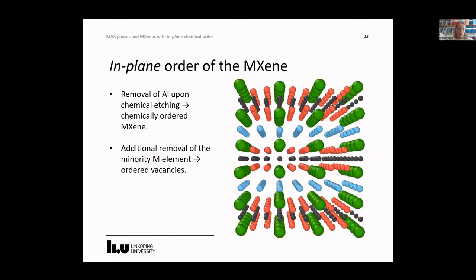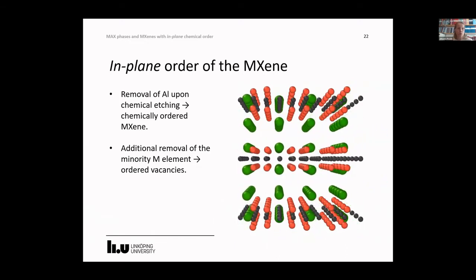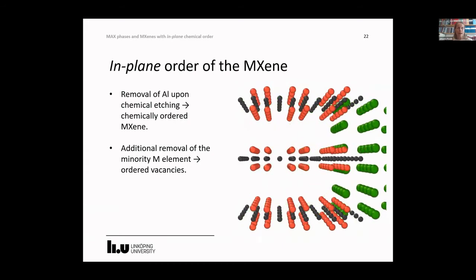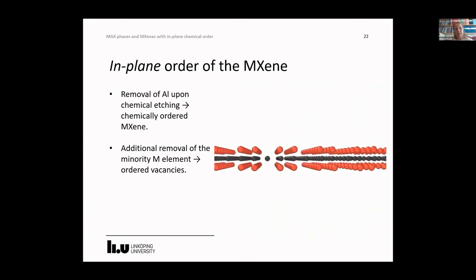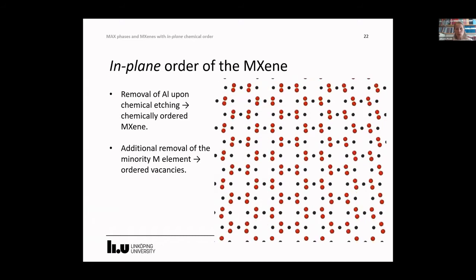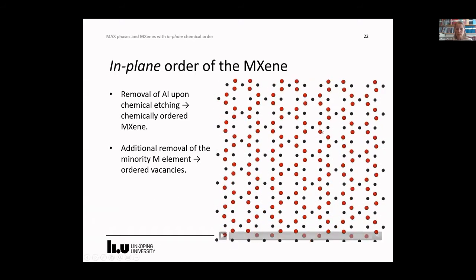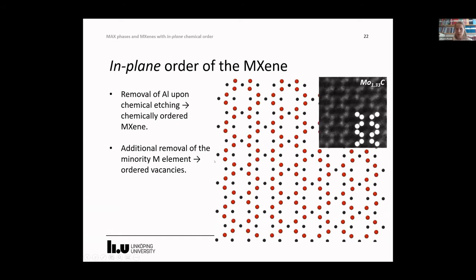Let's see. From this point forward, I will focus on MXenes. What is interesting with MAX phases is that if we etch them, we can remove aluminium like for traditional MXenes and then form a chemically ordered MXene, or we can get additional removal of the minority M element, leading to ordered vacancies looking like this. Here you see the corresponding TEM image.